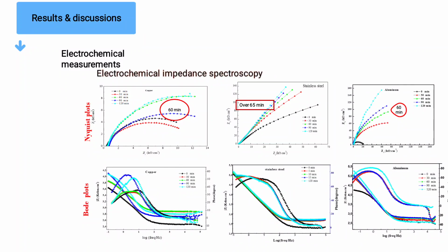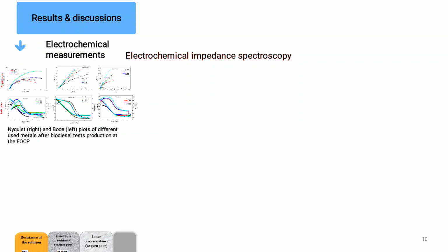The electrochemical measurement shows a flattened capacitive semicircle in the Nyquist diagram, indicating a surface inhomogeneity. Stainless steel and aluminium's corrosion resistance improves over time, likely due to the passive layer formation. After 65 minutes, aluminium and stainless steel continue to improve their resistance, while copper remains unstable, associated with the development of a protective layer.